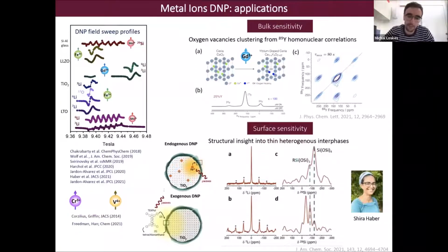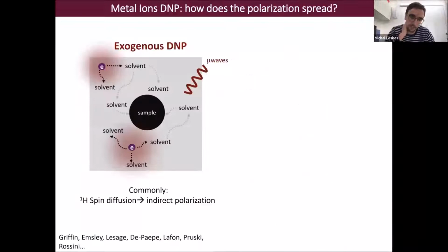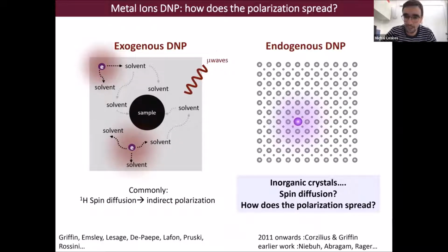So today I want to talk a little bit more generally about how this metal ion DNP approach actually works. As I told you before, in the exogenous DNP approach, we rely on proton homonuclear dipole couplings to transfer the polarization throughout the volume. But in most of our inorganic crystals, homonuclear dipole couplings are very weak because either the nuclei are low abundant or they have low gyromagnetic ratio. So the question that we were asking ourselves at the beginning is, how does the polarization spread throughout the sample? Or we also wanted to know if we're going to be very localized in enhancing nuclei that are only nearby, or in general, how the polarization spreads through the sample.